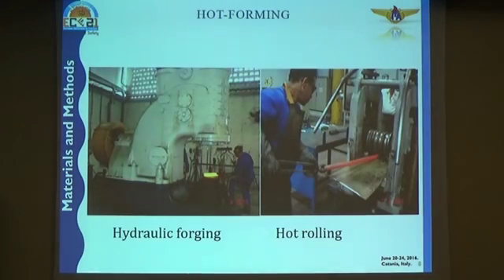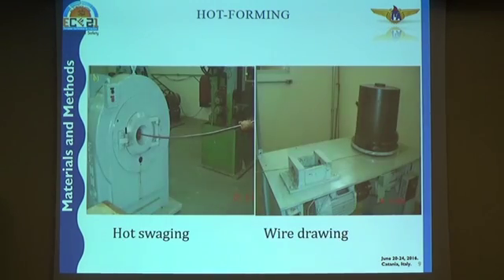Well, in order to have the wire, we hot formed the ingot. We used hydraulic forging, after which we hot rolled into bars. And then we did hot swaging. And at the end, we wire drew the ingot down to 2 millimeters in diameter. We have this wire with 2 millimeters.